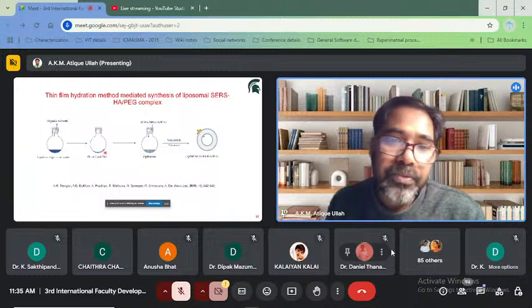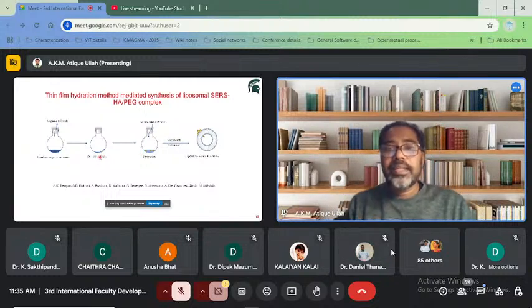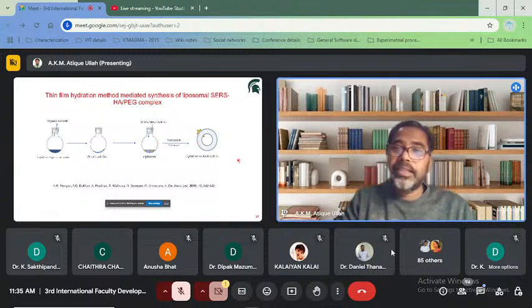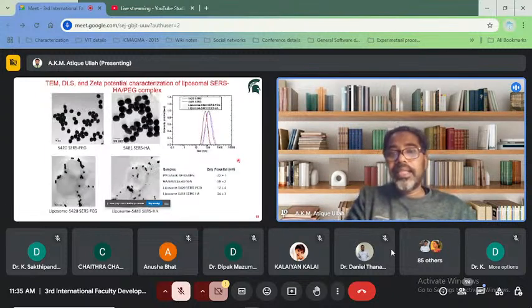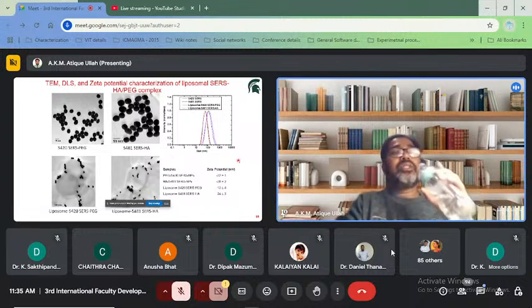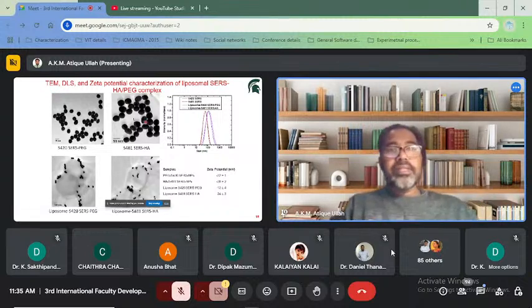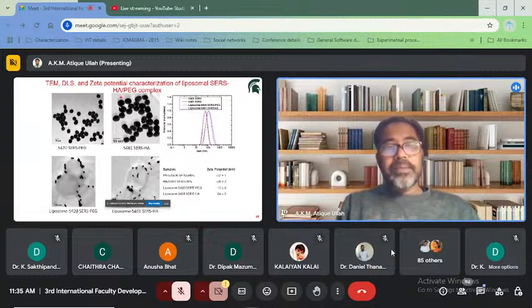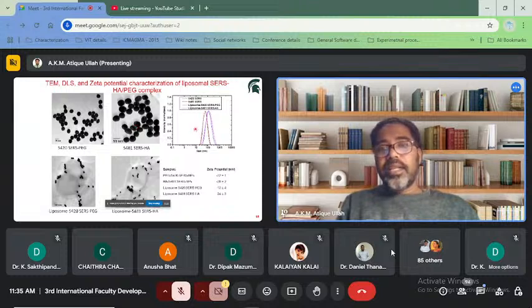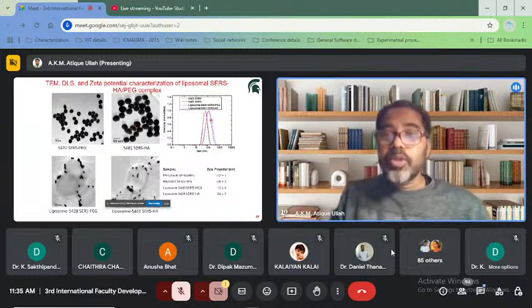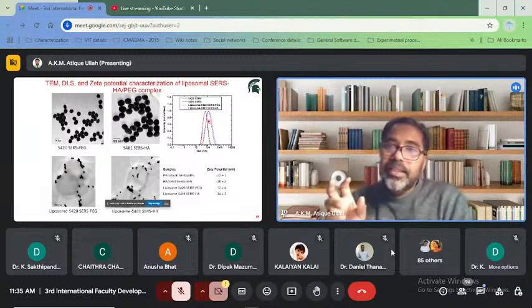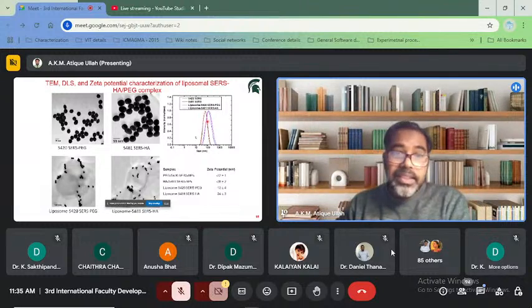A lipid film is formed. Then we hydrated with the SERS nanoparticles. We sonicated, and the complex is formed. Then the complex is characterized through TEM, DLS, and zeta potential. You can see these are the TEM images of the S420 SERS nanoparticles PEG. This is S481HA. This is the liposome one.